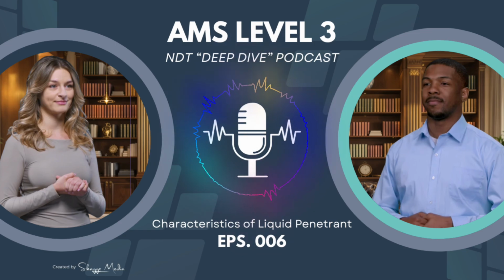Exactly. That's the capillary action. When the liquid wets the inside of that tiny capillary, the crack, it creates this pressure difference. It's quite a significant pressure, actually, drawing the liquid deep inside. And the dimensions here are just mind-bogglingly small. Think about a crack just half a micrometer wide. That's smaller than one of your red blood cells. Incredibly tiny. But even with a liquid having just moderate surface tension, that minuscule opening can generate huge capillary pressure. We're talking thousands, potentially tens of thousands of pounds per square inch. That's amazing pressure from such a small feature.